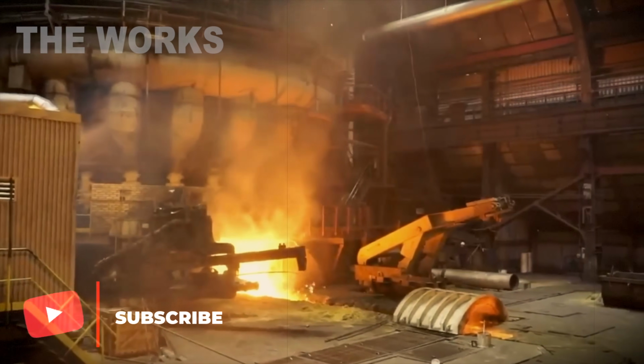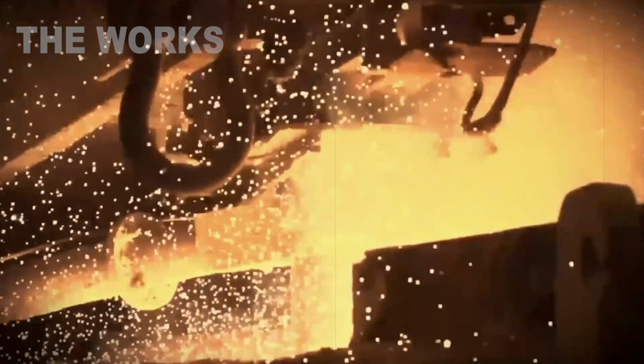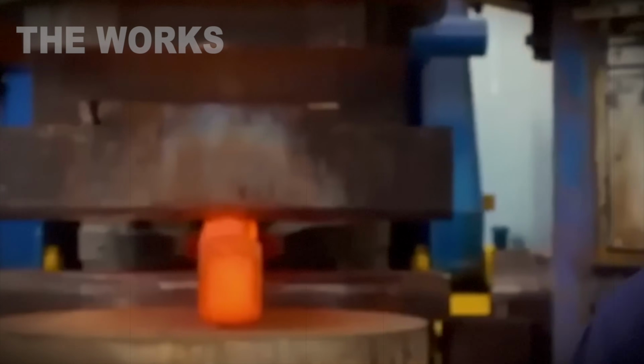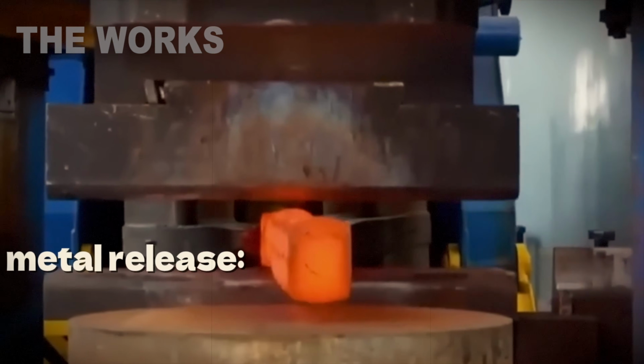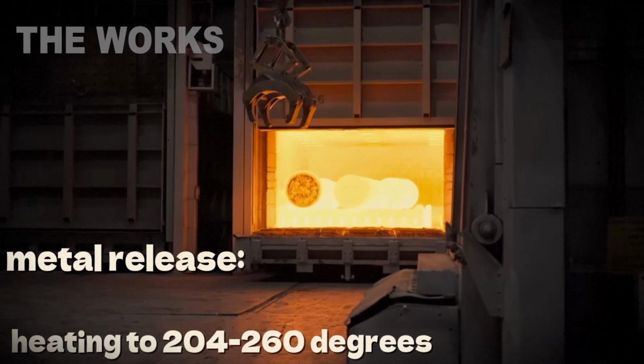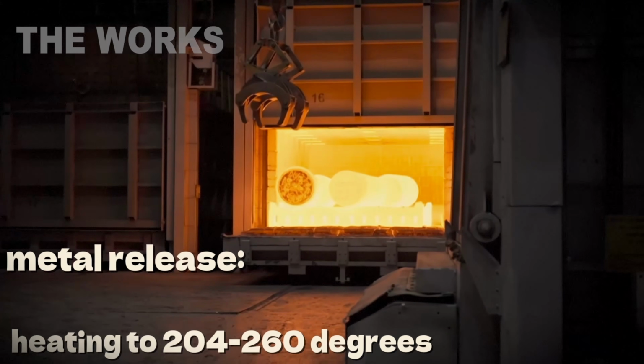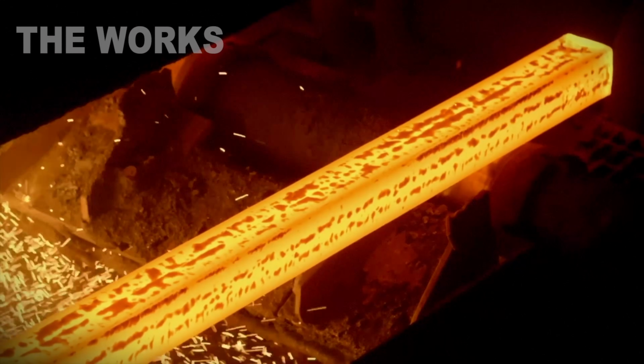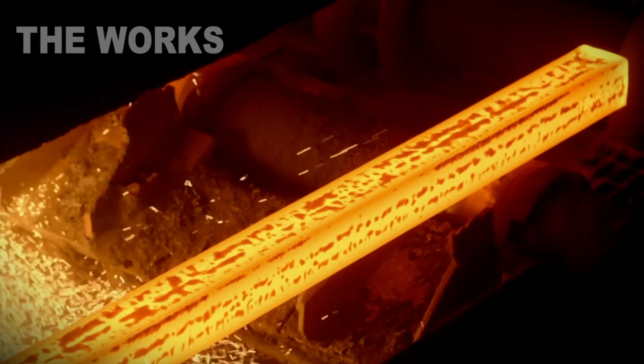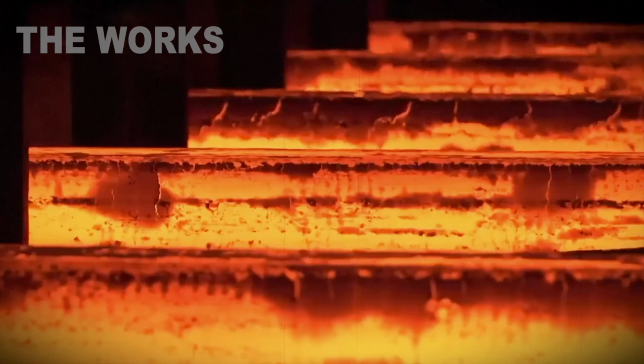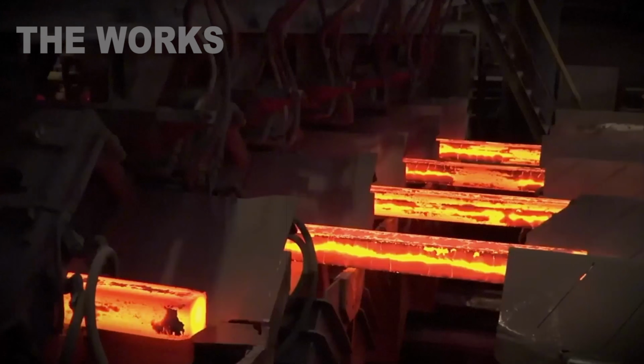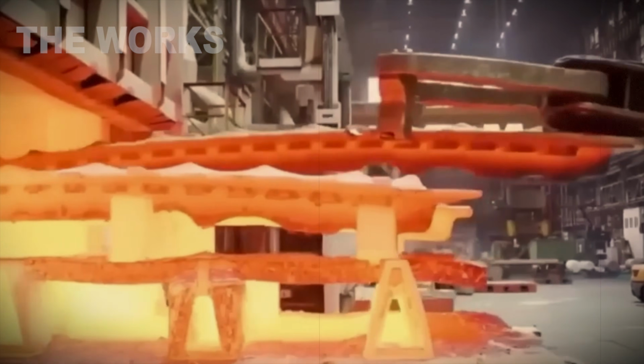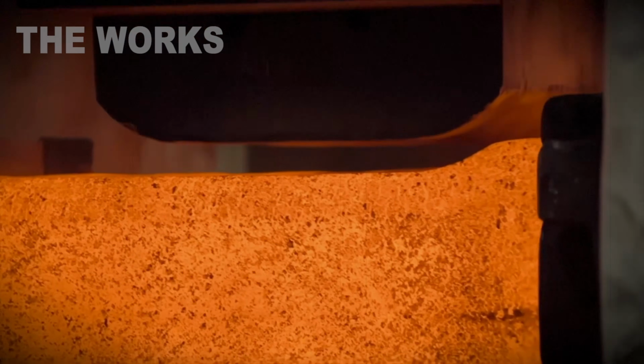But hardened steel is brittle as glass, one strike and it cracks. That's why there's a third stage, tempering. Heat to 400 to 500 degrees Fahrenheit, hold for 4 hours. This relieves internal stresses and adds flexibility. Hardness drops to 48 to 52 units, a perfect balance: hard enough not to wear down, flexible enough not to break.